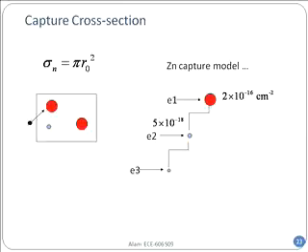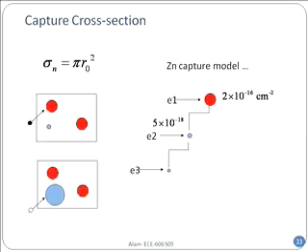So they disappear. On the other hand, once it has captured a certain number of electrons, for the hole it is very attractive because it is a charged thing, and therefore a hole can easily capture. So look at this number. As soon as it has captured an electron, for the second electron, E2, the cross section is small. It doesn't want a second electron, but it wants a hole. And in that case, for the first hole, you can see that it is 10 to the power minus 15, right? It's much larger.